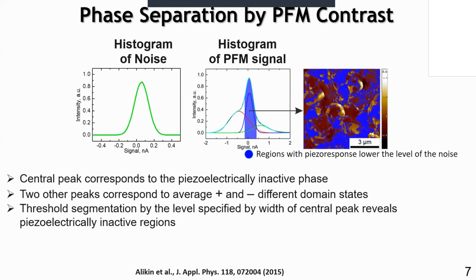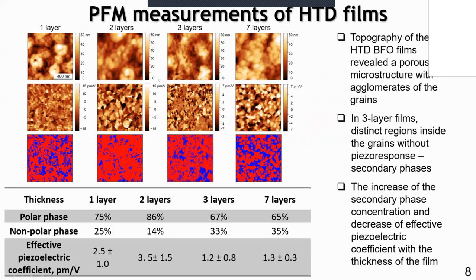I understand, but how do you obtain the image after this? How do we obtain the image? We take every point in the image, and in each point we determine whether the value of the piezo response is below the threshold or above the threshold. You determine the zero level, and shift. So there is the noise level, and if the response is higher than the noise, we use a color, a stronger color.